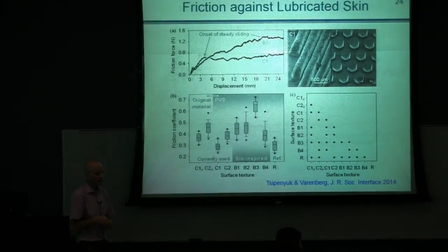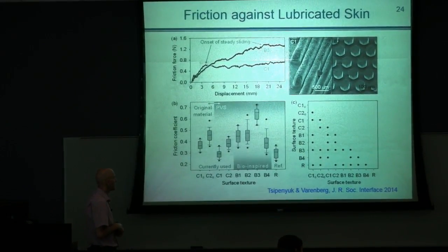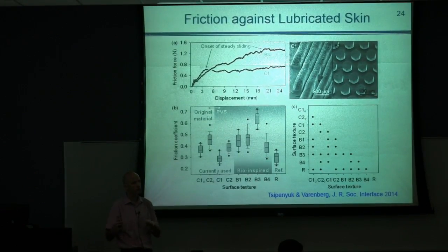Here, yeah. This is associated with the fact that you need to remove the shaving foam in this example from the interface, and it takes time. So actually here it is able to remove more lubricant, and obviously it takes more time. You can see that slopes here are more or less the same, so the rate of lubricant removal is more or less similar, but these structures have more capability to remove it more efficiently.